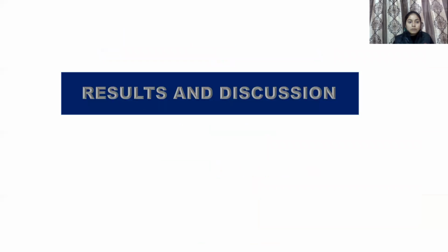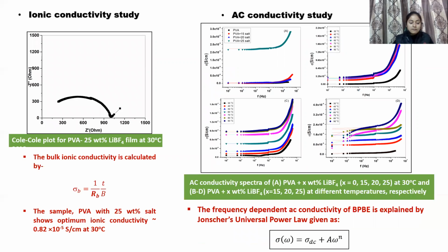Now moving ahead to results and discussion. First one is the ionic conductivity study. This is a Cole-Cole plot for PVA plus 25% LiBF4 film at 30 degrees centigrade. This plot shows two well-defined regions. First, at high frequency, a semicircular arc, which is associated with the bulk conductivity, and second, the low frequency spike, which is attributed to the electrolyte polarization effect at the interface.